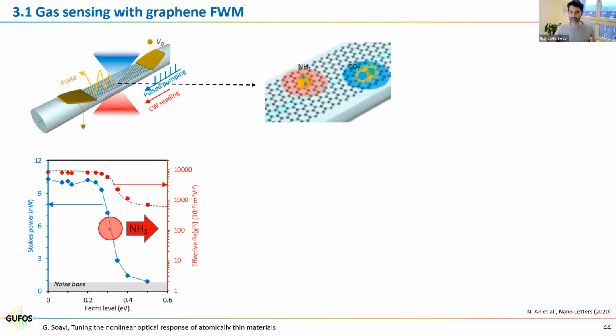And then we do the following. We flow gases onto our device. We can flow either CO2 or NH3, ammonia. I will focus only on ammonia because it's easier to understand, because what happens when ammonia is adsorbed on graphene is that electrons are transferred from ammonia to graphene. So basically you have an increase of the Fermi level. So if you look at this graph, whenever you adsorb ammonia, you decrease the four-wave mixing efficiency or the Stokes power. Okay, so let's see if this is the case.